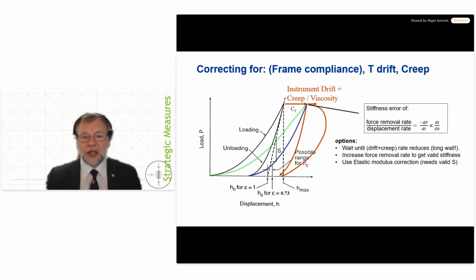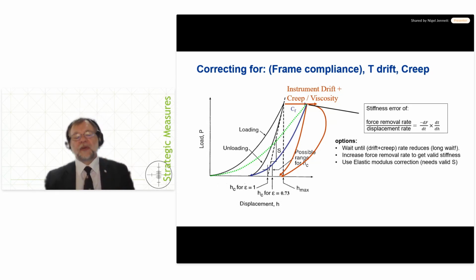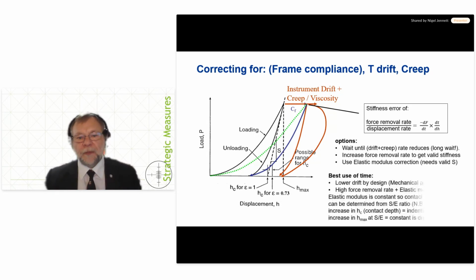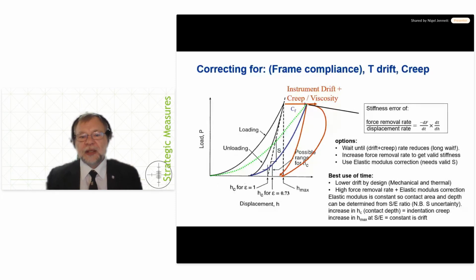However, increasingly, we're looking in the standards committee at using elastic modulus as an internal reference in each of the standards, and using that in a way so that we can actually determine what's happening. And this is not a new idea per se. It's been knocking around since Joslin and Oliver tried the P over S squared methodology to try and get rid of the area function. But the point is this: if you want to wait until a huge instrument gets to absolute thermal equilibrium and has zero drift, you'll be waiting a long time.